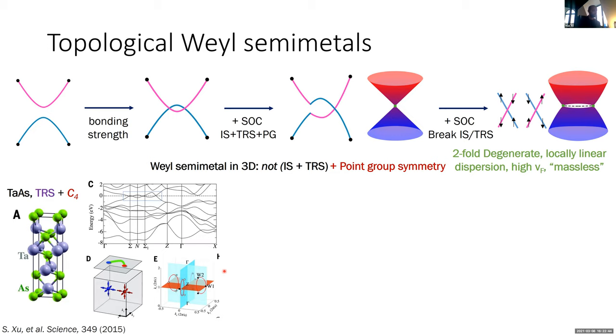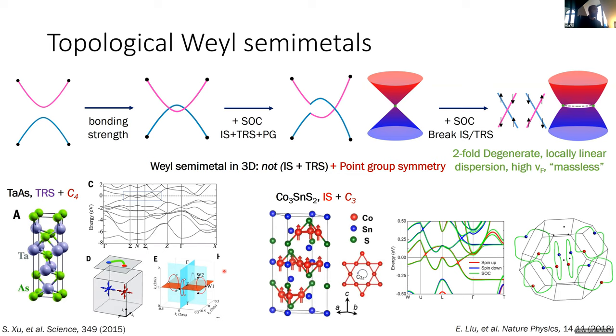More recently, time reversal symmetry was broken rather than inversion. And that was done in this kagome, so keep that in mind, cobalt tin sulfide, where you had a ferromagnetic coupling of the cobalt. So you ended up with an overall ferromagnet, which breaks time reversal symmetry, and also ended up with Weyl points.